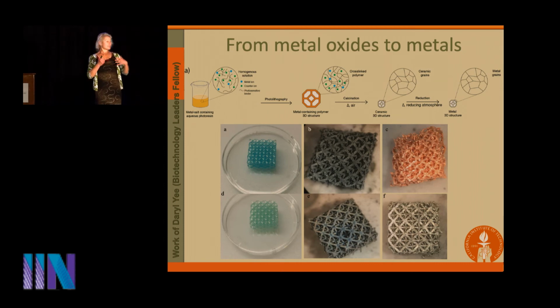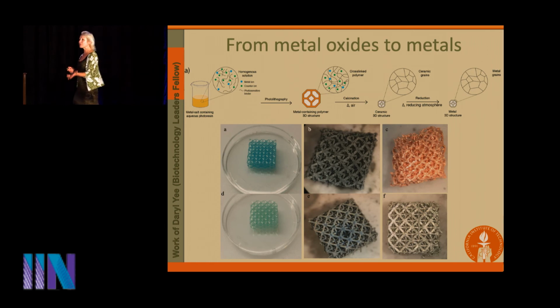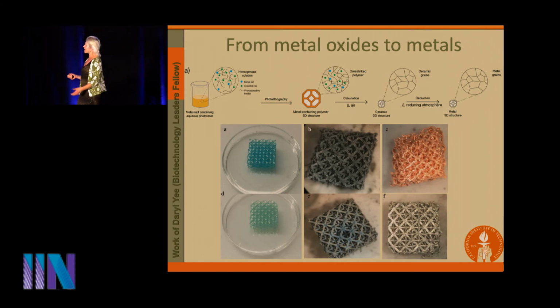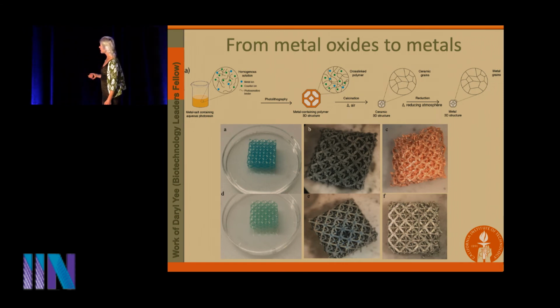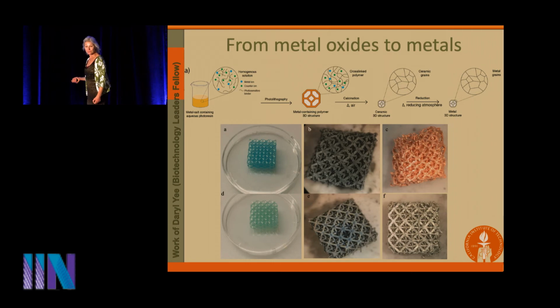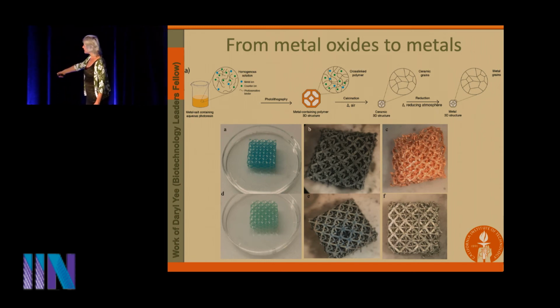Now, we decided to go backwards. At this point, Daryl said, well, I can make metal oxides using this hydrogel-based synthesis, so can I reduce them now to go back to the metals to make other metals not using the ligand exchange reaction? And so this is Daryl playing with nickel and with copper. You can probably tell which one is which, right? So this is the swollen hydrogel, with the copper ions here and the nickel ions here. You can see the characteristic color. Then we calcine them, burn them, so they become black. So these are the oxides, and then after that we're able to reduce them by placing them in the reducing environment, and you can see the color that emerges as shiny copper. So this is pure copper, and this is pure nickel.